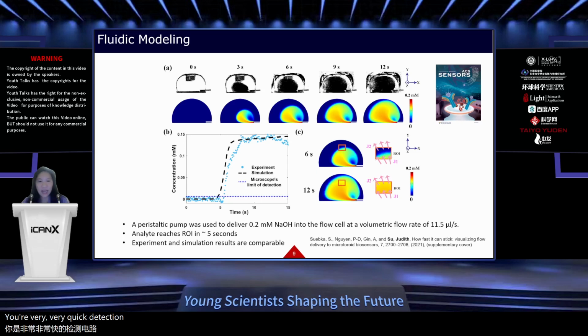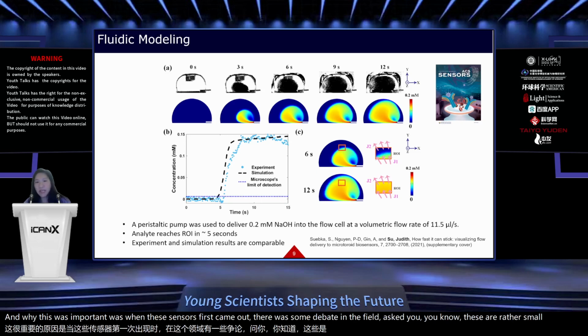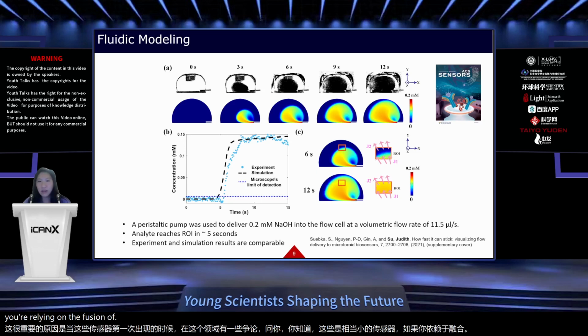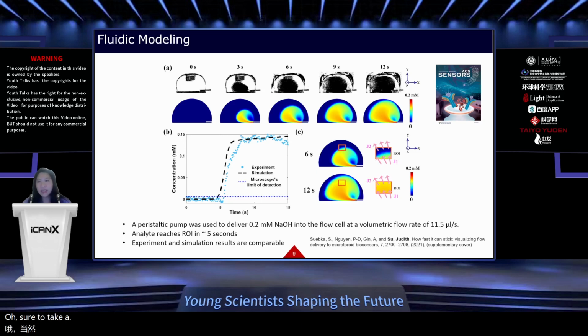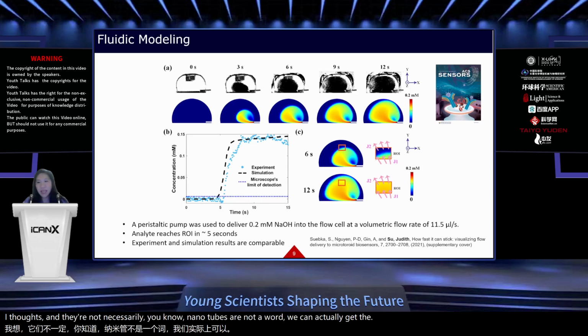We were able to get good agreement between simulation and experiment and get very quick detection within seconds, actually. Why this was important is that when these sensors first came out, there was some debate in the field: these are rather small sensors, and if you're relying on diffusion alone, shouldn't it take a very long time, like hours or days, for analyte to reach the surface of the sensor? But our simulations show that because our sensors are microsensors, on the order of 100 microns, and not nanosensors like nanotubes or nanowires, we can actually get detection quite quickly, which I believe is a great advantage of our system.